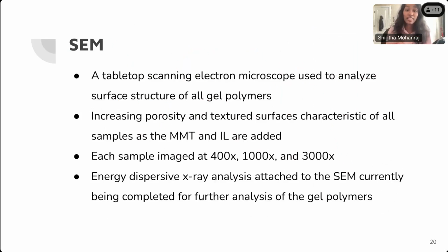And I also did scanning electron microscopy using a tabletop SEM to analyze the surface structure. And as the MMT and IL were added, there was definitely increasing porosity and textured surfaces, which made it more ideal to be using. And I imaged each sample at 400, 1000, and 3000 magnifications. And I'm currently working on energy dispersive X-ray to further analyze the composition of the gel polymers.